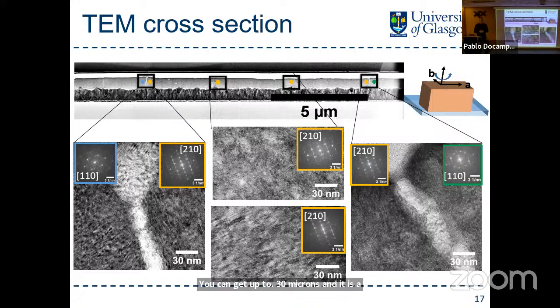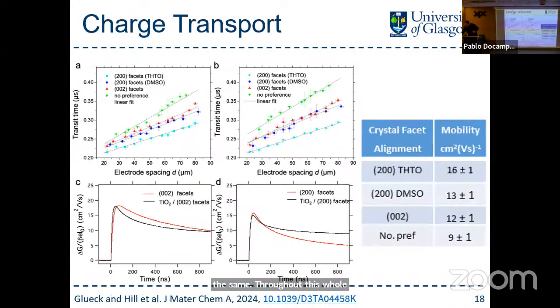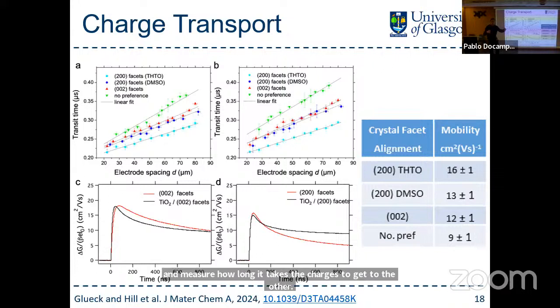So we did some TEM measurements. You can see the diffraction pattern is the same throughout this whole area, which shows that it is a single crystal. Again, that's not the important bit. The important bit is coming now. When you minimize disorder, when you make these crystals big, or oriented in the same direction, you minimize the grain boundary defects, okay? And that actually leads to an increase in the mobility of the material. So we did some time of flight measurements. We simply excite near one of the contacts, apply an electric field, and measure how long it takes the charges to get to the other side of the film, and you get a better result for these nice big crystals.